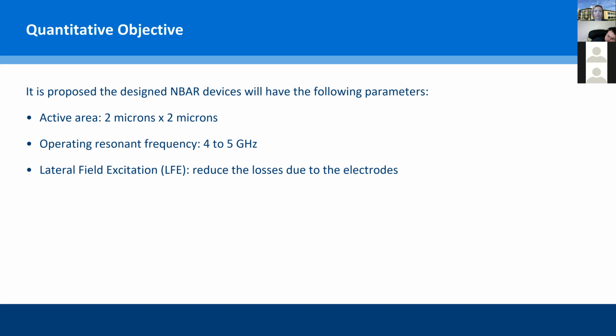The salient features of the device that we proposed: the active region that we used to design this resonator based sensor was 2 microns by 2 microns, as opposed to several hundred microns in the existing sensor technologies. And the operating frequencies that we obtained were between 4 to 5 gigahertz. So essentially, if you remember the Sauerbrey formula, we would be able to detect masses smaller than several femtograms, which is far better than the existing thin film acoustic resonators.